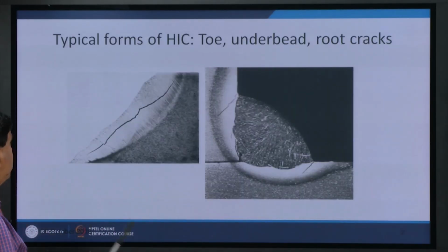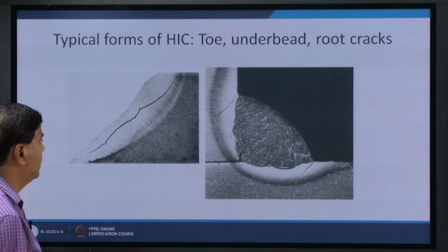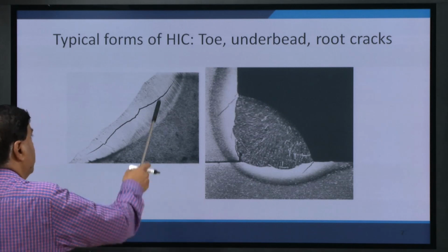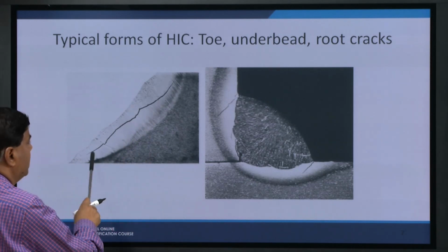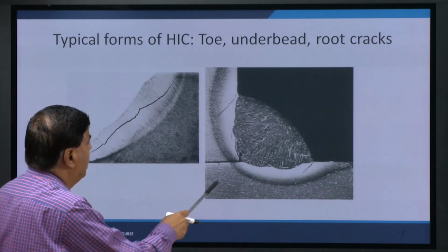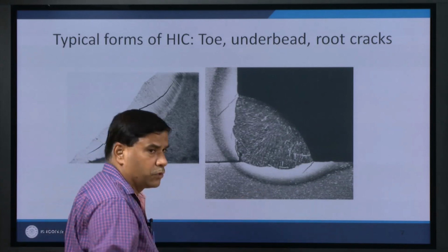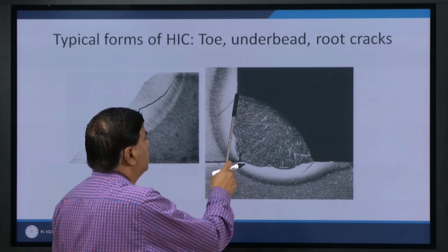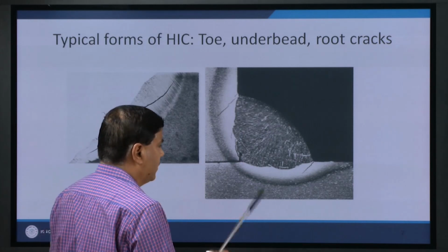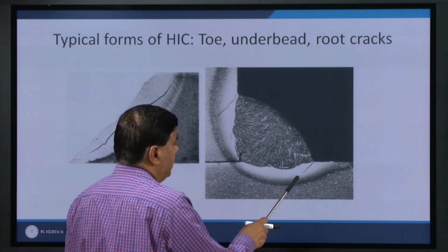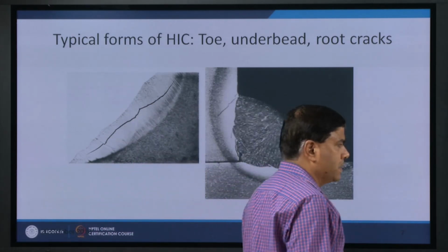So these are the typical diagrams or photographs showing the hydrogen induced cracks in the weld as well as in the heat affected zone. If the weld is sensitive to cracks, then it will have the cracks, and this is the crack in the toe region of the heat affected zone. Since the toe experiences stress concentration and tensile residual stresses, it promotes cracking if the conditions are favorable, like the hydrogen, hardness and martensitic transformation